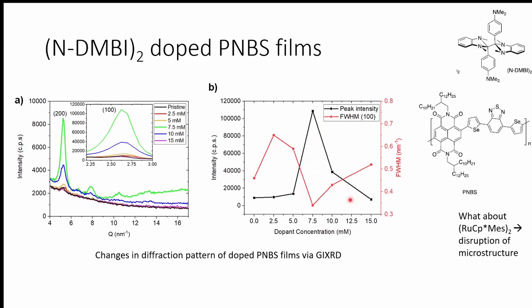So yeah, and then it starts decreasing. Now, as for the full width at half maximum, I wanted to track how the peaks are changing. Basically, it becomes wider as you first introduce your dopant, because when you're adding an impurity, it needs to get in between two stacks. So it will change how they're packed on top of one another. It will cause a disruption of your microstructure.